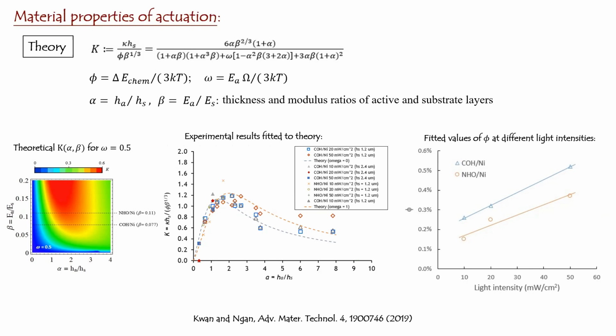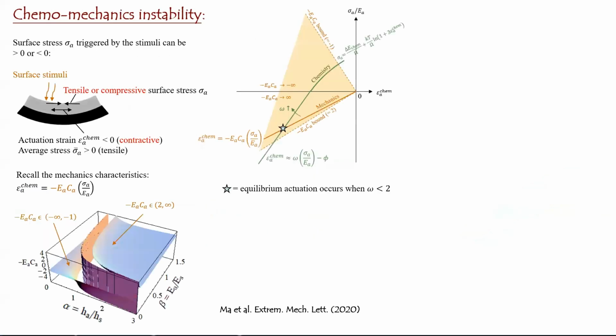Curvature itself is not a material property because it depends also on the substrate, right? But using this theory, you can work out the material properties like the activation energy versus light intensity. Okay, I know my time is coming up, so this is about my last slide, or last but one slide. There is also a very interesting phenomenon coming out from that chemomechanics consideration, and that is an instability. So the actuation can become unstable. When you hear the word unstable, it sounds bad, but in this case, it's good because when the actuation is unstable, it means that the actuation can be super large.